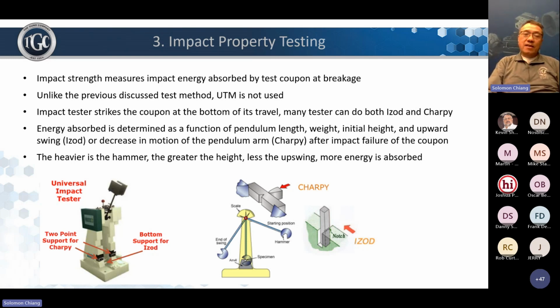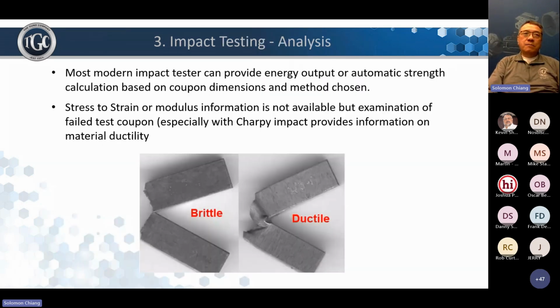And okay, with a UTM, we can look at the stress to strain curve and see if the material is ductile or brittle. In this case, we don't have the UTM, but we can always look at the sample after it failed. The brittle one is on the left, it just broke into two halves. The ductile one, you can tell it's absorbing some energy, so it hangs in there for a little bit until it failed. So just by looking at it, you can tell whether the material is ductile or brittle.